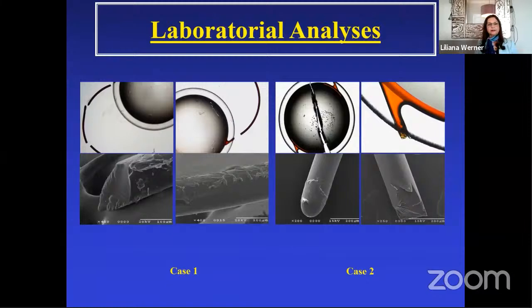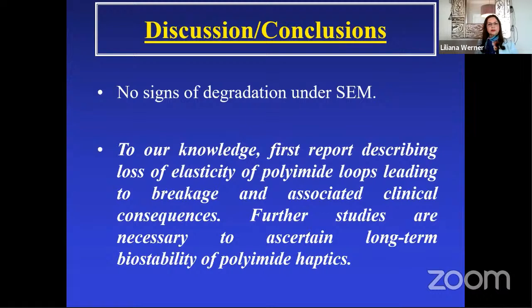There was no sign of degradation of the loop material under scanning electron microscopy. However, there was a loss of elasticity of the material, and only by touching the loops with forceps, further breakage was observed. The spontaneous breakage of the loops in these cases led to IOL dislocation. Further studies are necessary to ascertain long-term biostability of polyimide haptics.